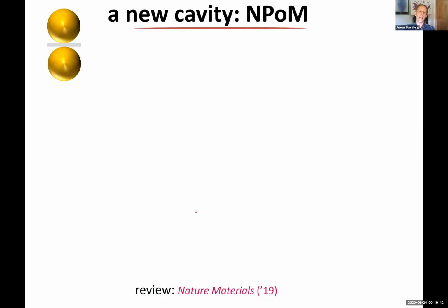So what we were interested then is, can we confine light between metals? And as I'll show you, the best thing that we could do is actually make a very, very small gap between two metals. So what we wanted to do is to control this gap size to the nanometer scale. So we started by trying to control that gap size by putting graphene in between two gold nanoparticles. And the problem is that once you've got one gold nanoparticle on here, the second one doesn't want to go into its vicinity. It's very hard to make this happen. So that's not a good system to make it work.